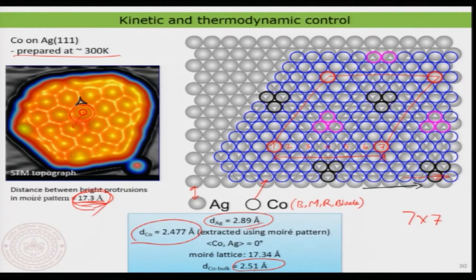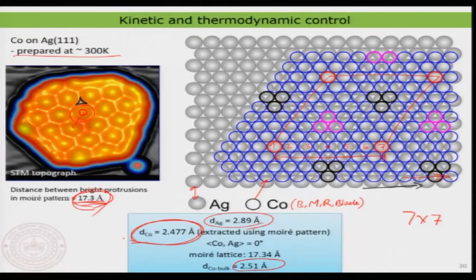So that means their orientation is zero. That's an experimental input, and the superlattice distance is also an experimental input. By putting that into account, I can basically just regenerate. And what is most important is that I can now recalculate the modification in the cobalt lattice. It is now basically compressed very, very slightly compared to the bulk lattice.